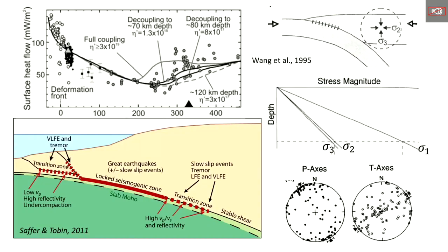One more thing. The stress state, we're talking about 20, 30 MPa shear stress. That's a lot bigger than people might guess based on what types of phenomenon lead to the triggering of slow slip events. All right. So how well do we know the stress state? And I, as a scientist who's been around for a while, have some icons that the subducting interface is weak, and 2 of them come from right from this area. And 2 of them are presented in a paper by Wang from 30 years ago.